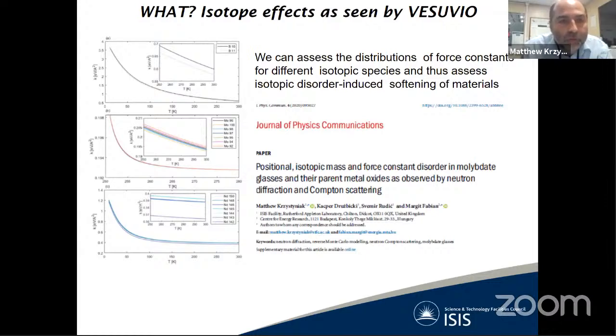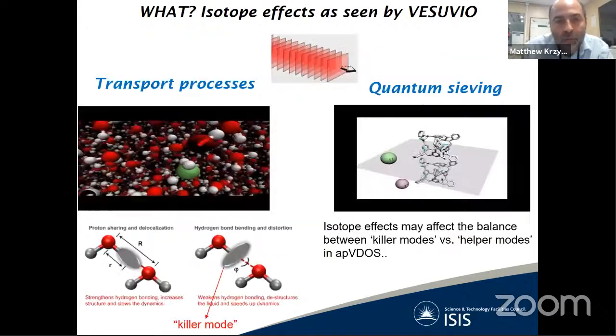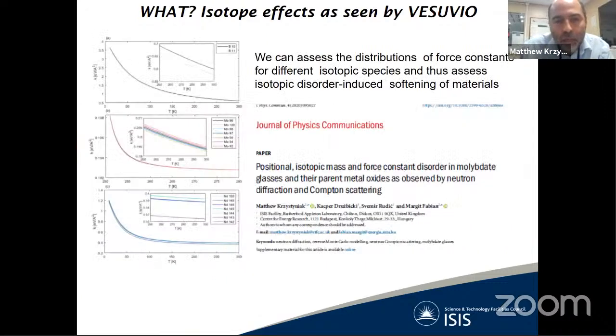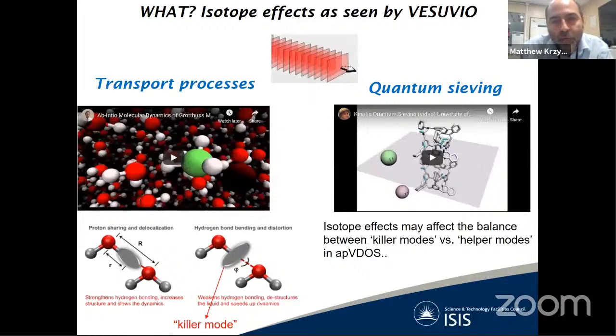There are very interesting results showing that there are, for instance, non-monotonic relationships between the magnitude of the disorder of the force constants and the temperature. And some of the nuclei exhibit more marked non-linear relationships between the magnitude of disorder and temperature than the others, which is one of the signatures of the stability of the whole system as a function of temperature. In terms of isotope effects seen by neutron Compton scattering, two very important applications are transport processes and quantum sieving.